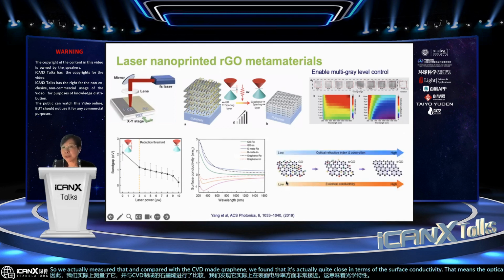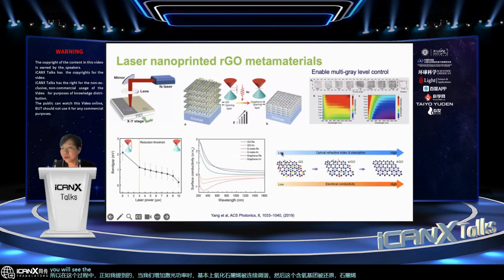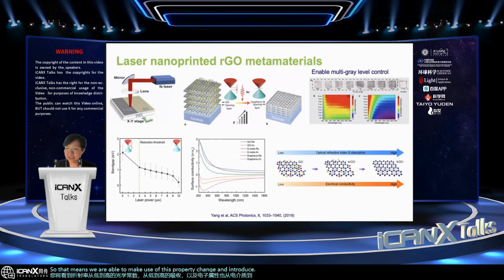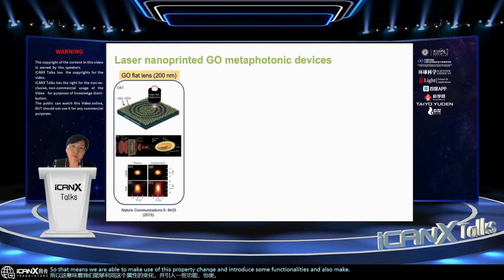So during this process, as I mentioned, when we increase the laser power, graphene oxide is continuously tuned, and the oxygen-containing groups are reduced gradually and then eventually fully reduced. You will see the optical constant, refractive index, from low to high, the absorption from low to high, and also the electronic property from dielectric into conductive. So that means we are able to make use of this property change and introduce some functionalities and also make some devices. Now I will show what kind of devices we can make.